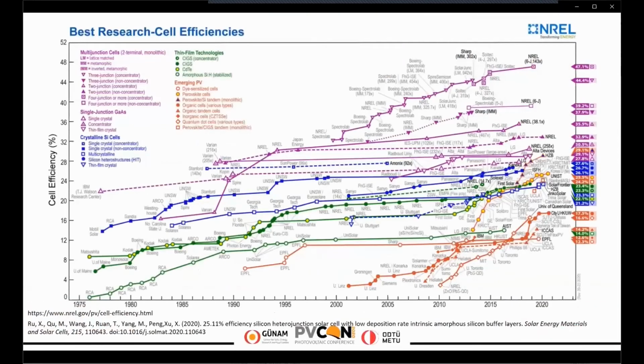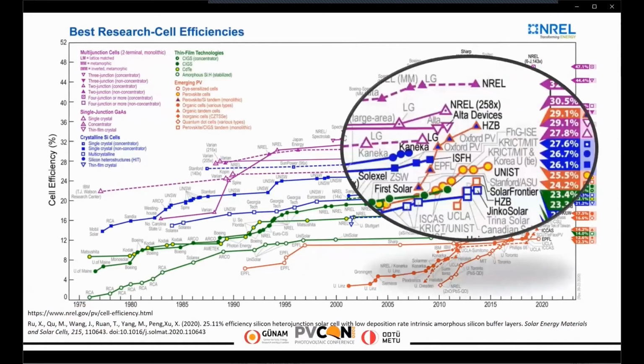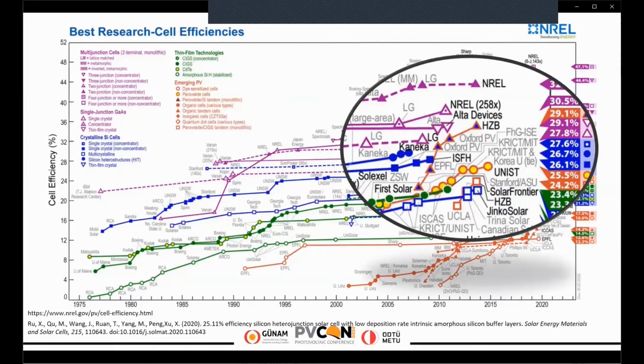I would like to start with the well-known best research cell efficiency chart from NREL. As you can see from the chart, efficiency values are increasing year by year for almost all technologies. But in this chart, I would like to focus on the silicon solar cell part. The record efficiency on silicon solar cells belongs to the heterojunction IBC structure. The record efficiency was achieved by Kaneka with 26.7%. For single junction solar cells, the record efficiency is 26.1% with a TOPCon IBC structure.